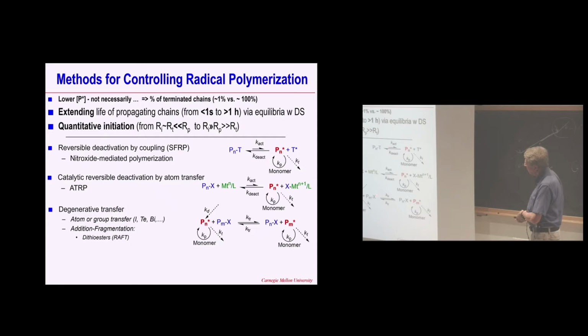You just reshuffle this atom or group between these chains, so this one will become itself dormant and would activate this species, which can propagate once or twice and go back to a dormant state. So in all of these systems, if you want to have proper control, you need to allow propagation maybe 1, 2, maybe 5 times, and then convert it to a dormant state. It would be the same here, maybe 1 or 2 monomer additions, and then conversion by exchange from active to a dormant state. So I will show you some examples of these systems, including alkyl iodide, sometimes derivatives of tellurium or bismuth. And now probably one of the most important are dithio compounds, dithio esters, or xanthates. These are so-called RAFT polymerization reagents.